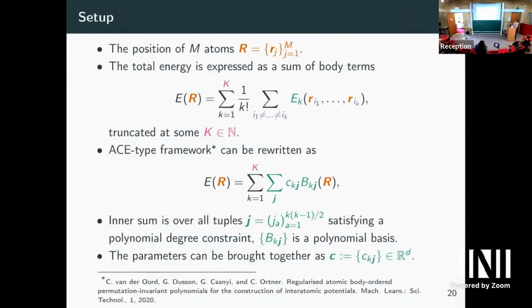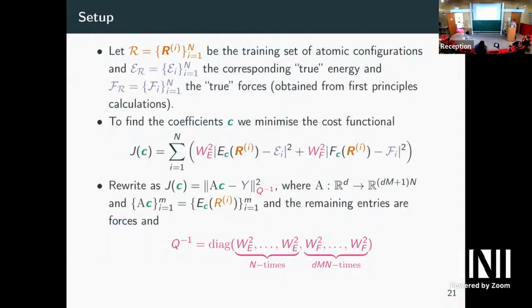And so the idea here in the setup is that you want to study some material system, and you do these extremely expensive calculations for about a few thousand configurations that are representative of different phases of a material depending on what you model, and you collect them as quantum mechanical energies, and forces as well. And then the point is that you want to fit a function that will somehow resemble the behavior of quantum mechanics in between these configurations.